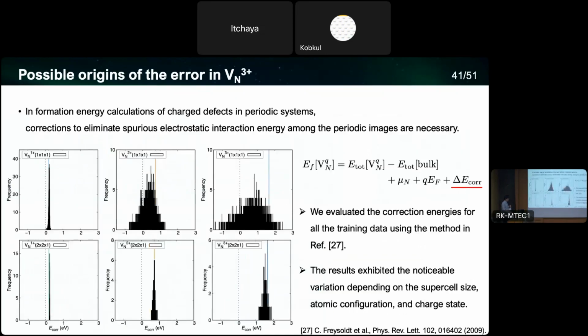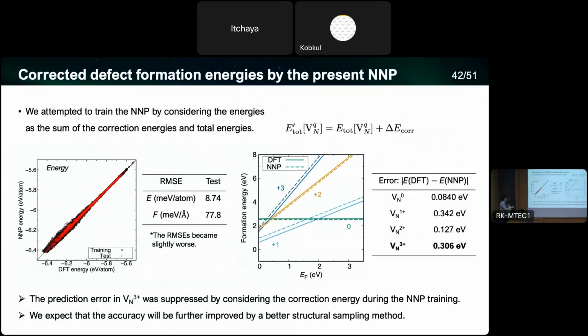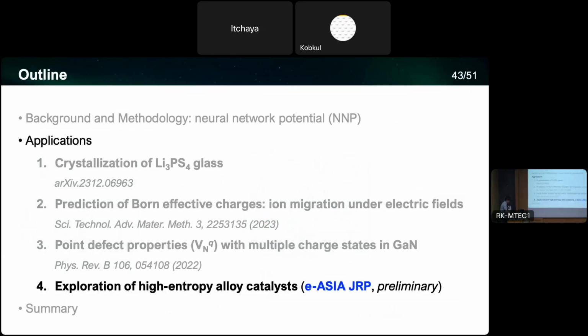So those specific structures are not sampled in our training dataset. In addition, some of you may know that we need to correct the energies when we introduce a charged defect. By doing the correction technique, we have confirmed that depending on the charge state and the structures, the correction needs large variations. So by including such corrections, we retrained the neural network potential, and we got the refined one. And the defect formation energies improved, as you can see in the graph. In this study, we stop at this stage, but by changing the sampling techniques, we expect that the prediction performance can be further improved. So I will move on to the last topic.